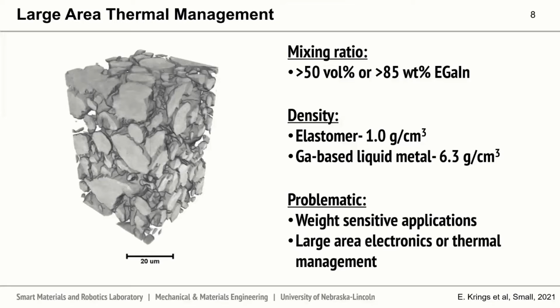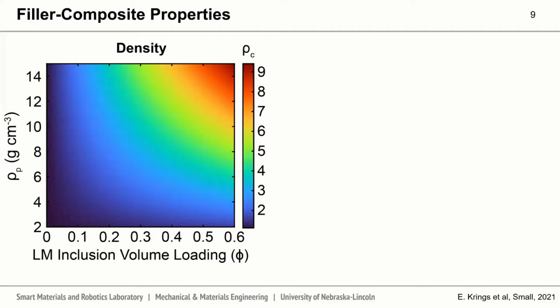So in this project, we began to really try to understand and uncover the influence of the properties of the filler on the ultimate properties of the composite. Here we're looking at the density of the particle filler on the left as a function of the loading of this particle filling elastomer matrix. The color map describes the density of the composite. And what we see here, as expected, as the density of the particle filler increases and the volume loading of that particle filler increases, the density of the composite increases.